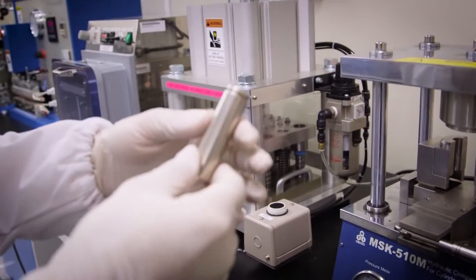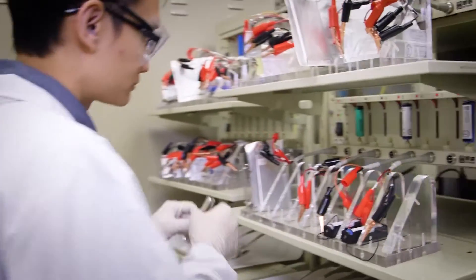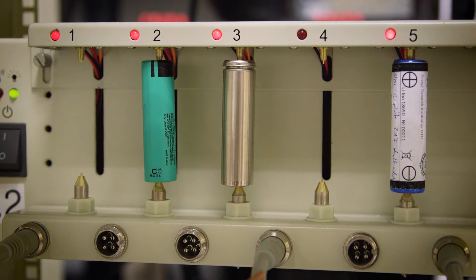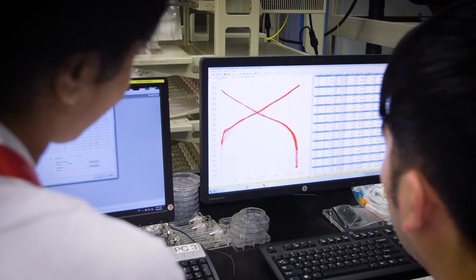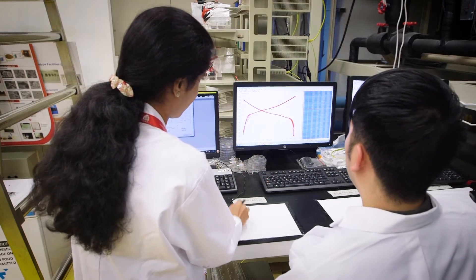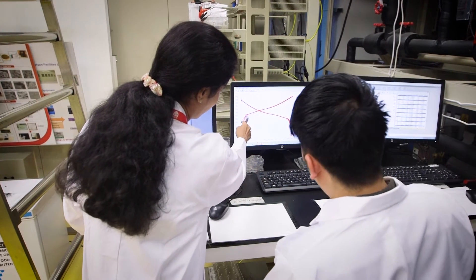Once the battery has been fabricated, then we do the battery testing. We put the battery into several thousands of cycles of charging and discharging to test the efficacy of these batteries in terms of voltage, in terms of current stored, and in terms of longevity. For this configuration, we are getting about 1500 mAh capacity. It has been running for about 500 cycles and it is stable — about 95% cycle retention. The batteries here have proven very, very effective so far.